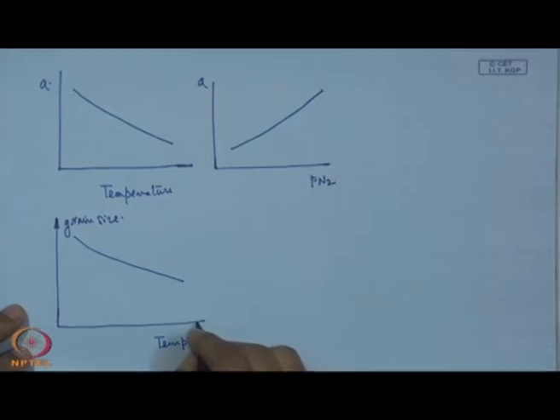This happens for the simple reason that when the molecules are formed on the surface, because of the low mobility of the adatom, there is less diffusion on the surface. Because of this less mobility, the adatoms cannot join together and become an integral unit, and there remains a lot of void space, porosity and gaps. This can be filled in if we have better mobility of the adatom, and this can be enhanced simply by increasing the temperature.